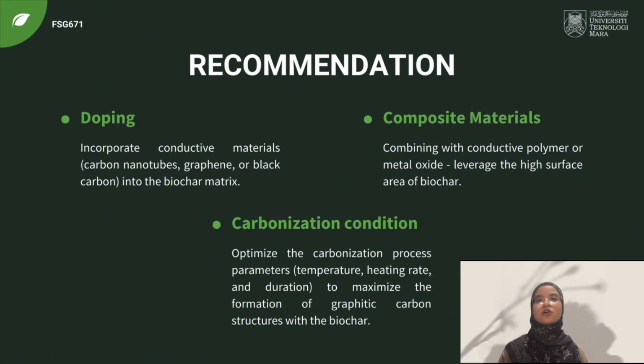The first one, incorporate conductive materials into the biochar matrix to significantly increase conductivity. Next, use composite material by combining the biochar matrix with conductive polymer or metal oxide to leverage the high surface area of biochar to increase the number of active sites for electrochemical reaction, enhancing the energy storage capacity. And lastly, optimize the carbonization process parameters such as temperature, heating rate, and duration to maximize the formation of graphitic carbon structure within the biochar.